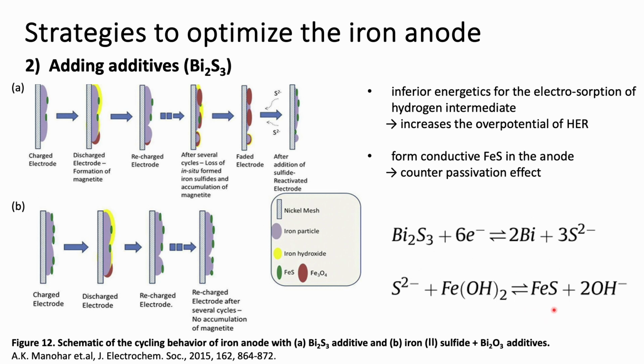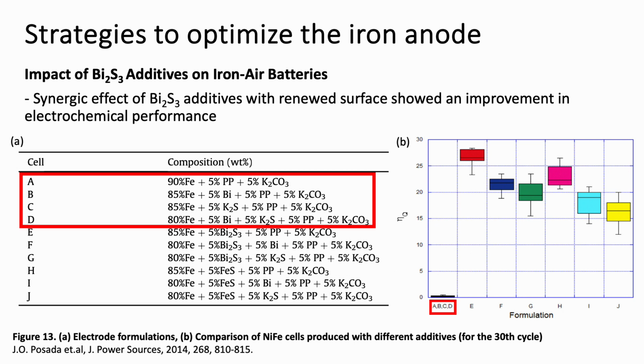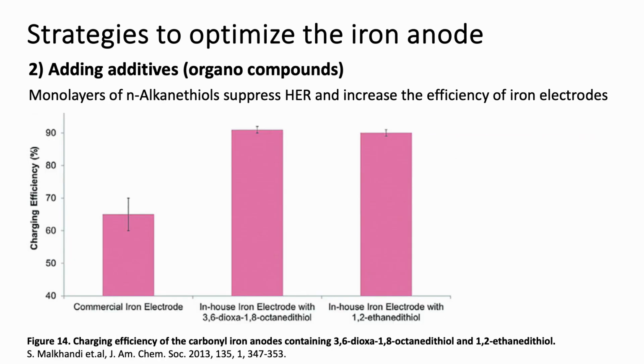On the contrary, Posada and others argued that the improved electrochemical performance with bismuth sulfide additive should be ascribed to the synergetic effect between bismuth sulfide and renewed surface, and the presence of elemental bismuth itself only influences Coulombic efficiency a little.